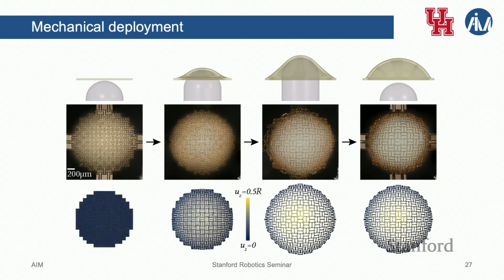And simple FEM analysis confirms this exact progression. And what's more important, with the FEM, we can confirm once the indenter has left, this shape is indeed at a strain energy minimum, which shows once we deploy the structure, it will stay deployed. I mean, physically, it does stay deployed anyway, but even in absence of plasticity, so we didn't model plasticity in this particular system, it still stays in that deployed shape.